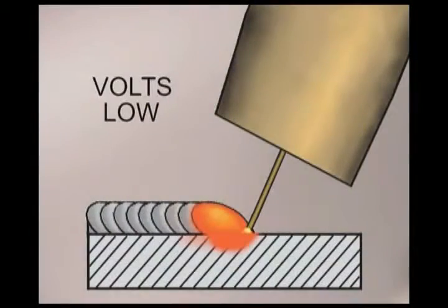If the voltage is set too low for the wire speed, the arc length is shortened, allowing the wire to run into the puddle. The arc may be erratic, and there's not enough heat to melt both the filler metal and the base metal, so the puddle doesn't flow out on the sides. The finished weld bead will just stack up.